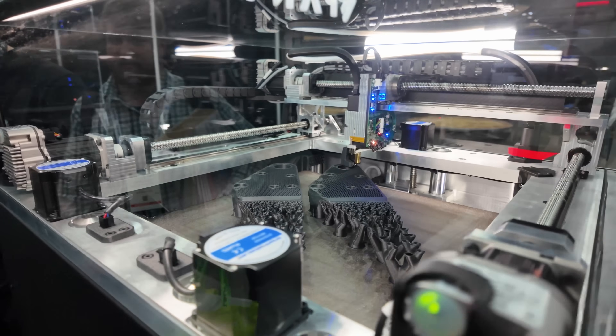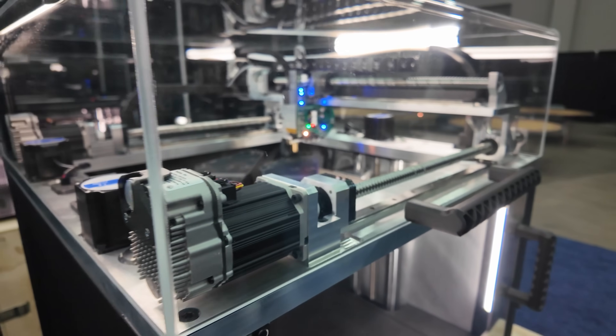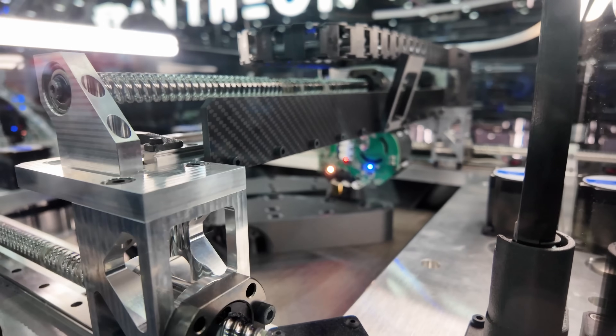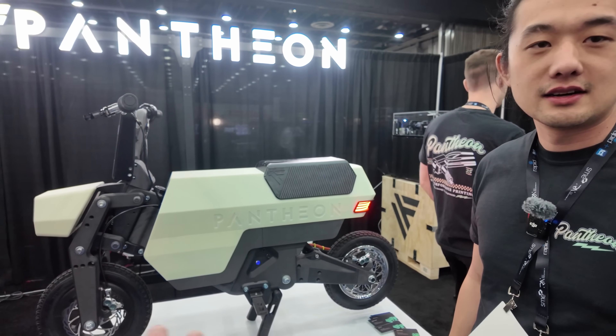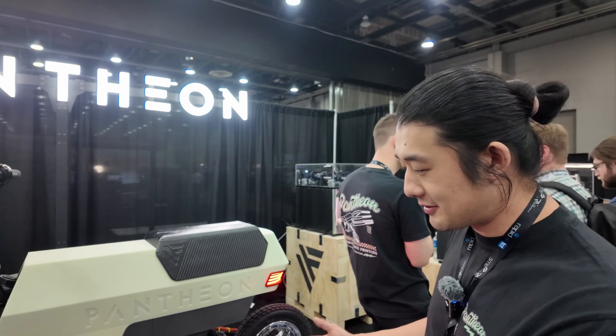It's 400 millimeters by 400. Parts needed to be stronger. So we got the deposition density way higher by improving motion and deposition accuracy. We're getting around 60 MPa on Z bonds in nylon, which is pretty absurd, and 120 on the XY — enough to make a part that would have been cast aluminum before. And you've taken this thing off ramps. Yeah, and this is fully 3D printed — it's not like there's an aluminum extrusion frame in it. It's just printed.